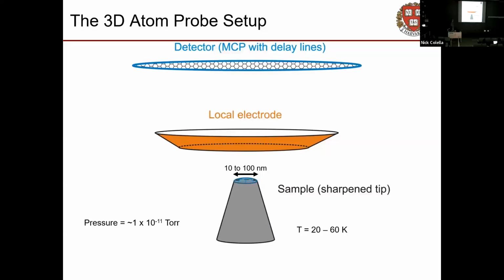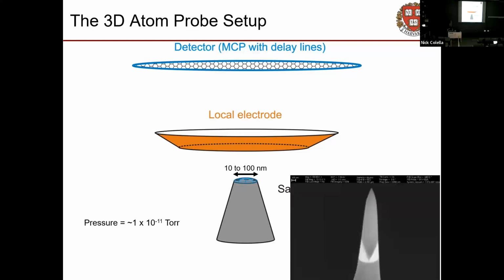We make a little sharp tip, and by sharp, I mean really sharp. I mean, we sharpen your piece of material up until the point is like 10 nanometers, like 100 atoms across. Cool. Why would we bother with that? Well, we then stick it under an electrode, little cone-shaped electrode. Here's what the samples actually look like, by the way, by the time we get done with them. Little pointy needles, as imaged by SEM.